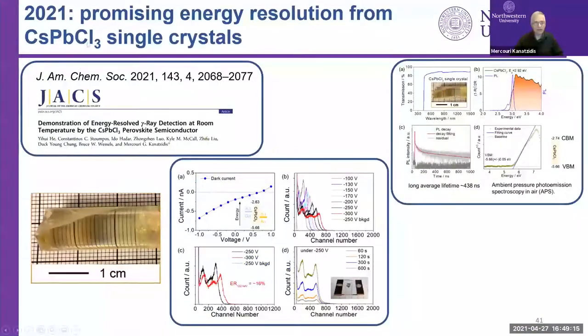And also the cesium lead chloride, we just published a month ago, and we managed to also detect gamma ray spectra. As you see here, we have a photo peak. The resolution is much lower at about 16%. The bandgap of this material is a little bit higher than we would like it to be. That's why it is almost colorless, light yellow, but it does have a lot of promise as well. And we haven't done a lot of work on these materials yet. We hope to do more and evaluate it for X-ray detection in the future.